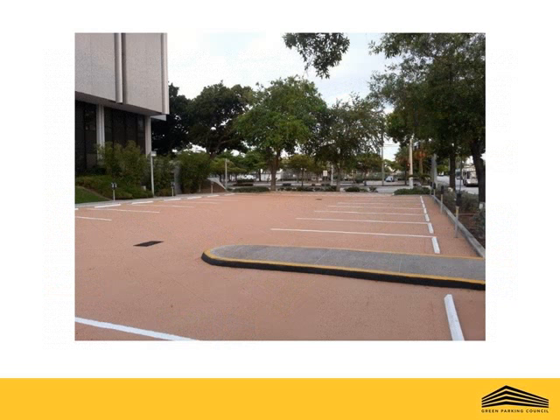We took temperature readings immediately prior to the installation, and we posted in the early morning, sunny day, about 104 degrees on the surface. After 2 days of installation on a very, very similar day, the temperature surface was about 91 degrees. And of course, because the surface is solar reflective, it reduces the amount of heat absorbed during the day and consequently released during the night, which is a very important component, and you've heard it, of course, before from Haley and Ben.